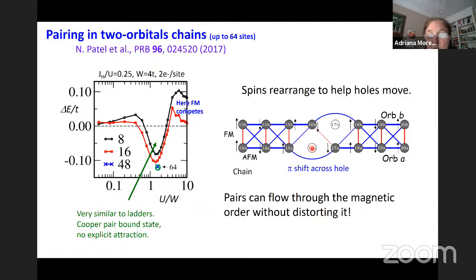We also notice that they go into sites where there is a pi shift across the hole. If this were replacing the electron originally here with a spin down, this guy would have to have a spin up, but the presence of the hole causes a pi shift. The other hole goes into the next nearest neighbor site, but in the other orbital, and there is also a pi shift.